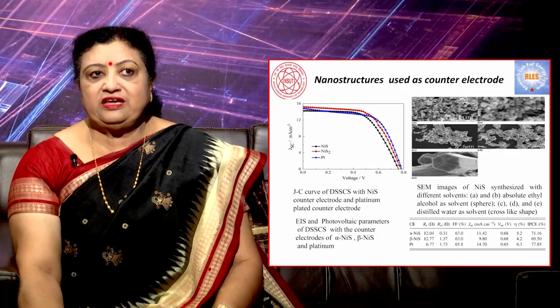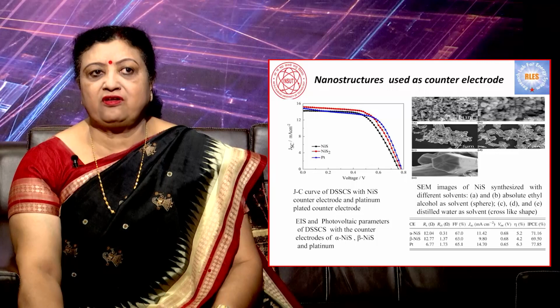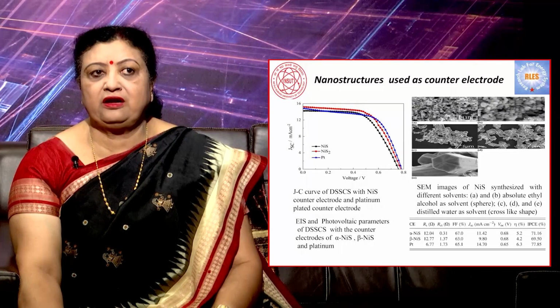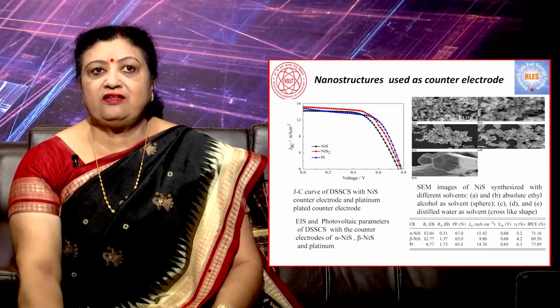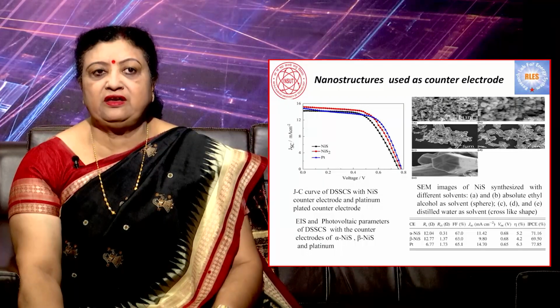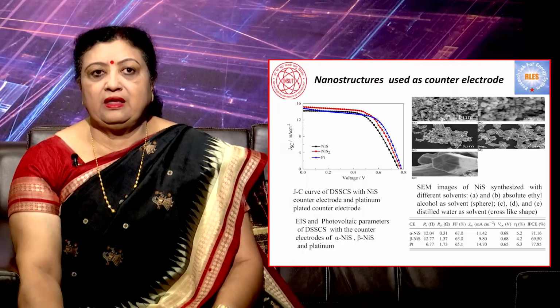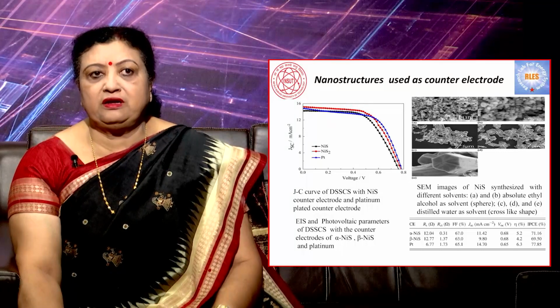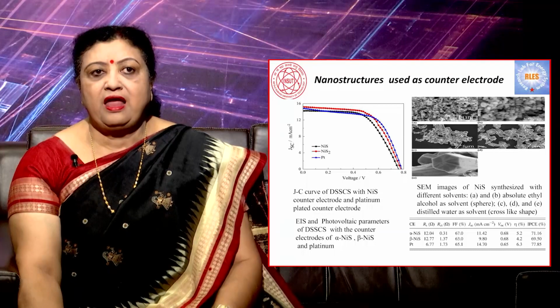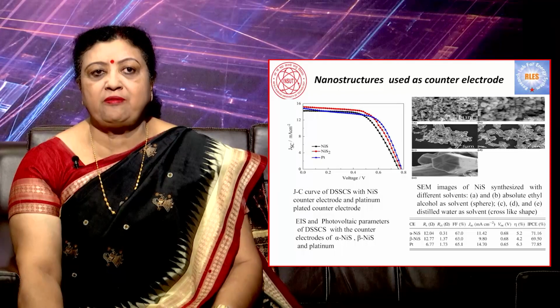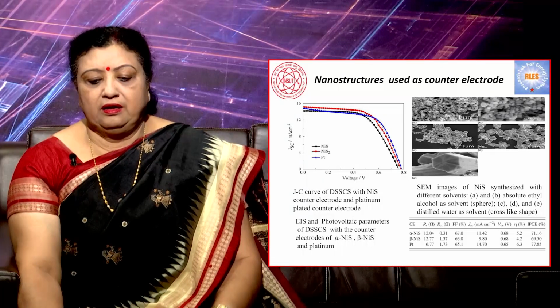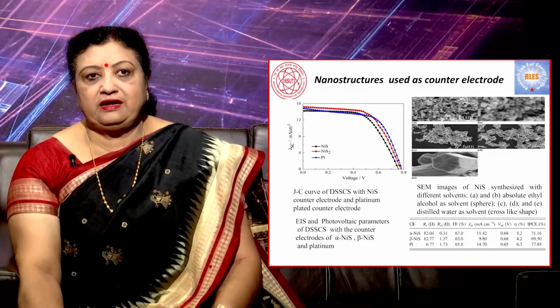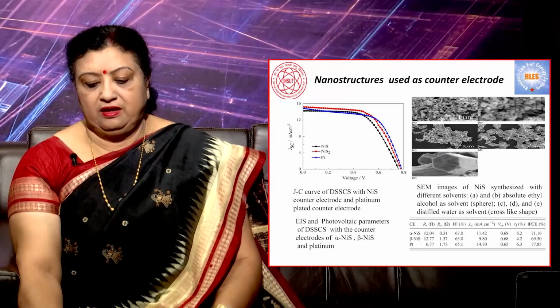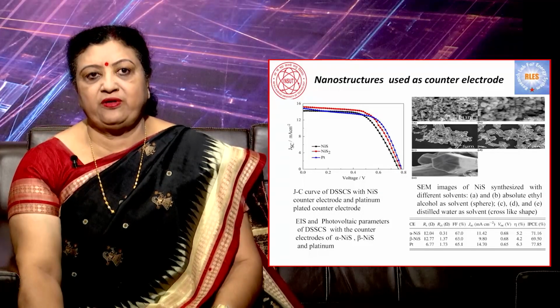Here the J-V curve of the DSSC with the NiS counter electrode and the platinum plated counter electrode has been described. The same image shows NiS synthesized with different solvents, absolute ethyl alcohol as solvent and distilled water as solvent, and the various properties which we have obtained, like fill factor, current density and efficiency, are all given in this particular table which has been provided here.